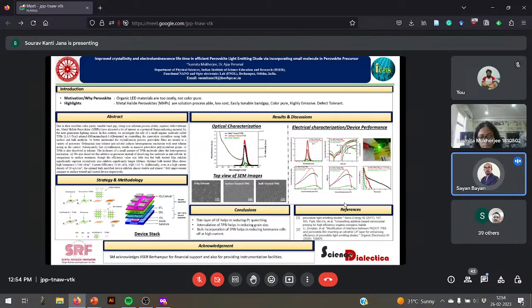No, actually, in most of the devices where we have a layer-by-layer system, there is interdiffusion between two layers. That actually hampers the photoluminescence efficiency. So I think you can check whether all those films were chemically coated. Yes, the HTL layer is spin coated, and the other layers are thermally deposited. In that case, you can check whether there is diffusion of atoms from one layer to another, because that may quench your luminescence efficiency a little bit. Yeah, sure, sir. I will look into this aspect.